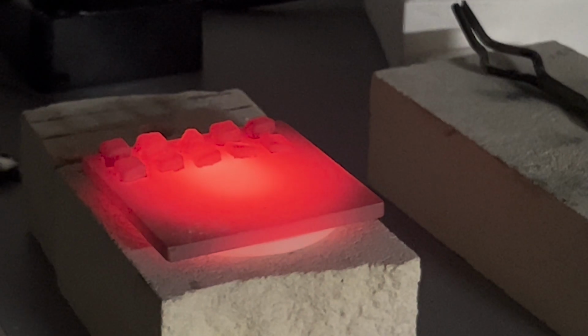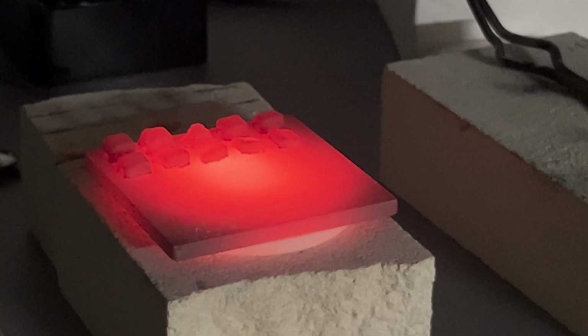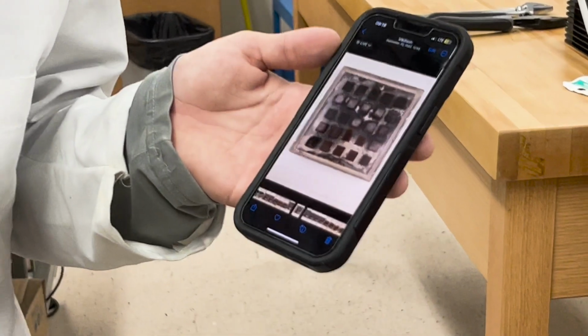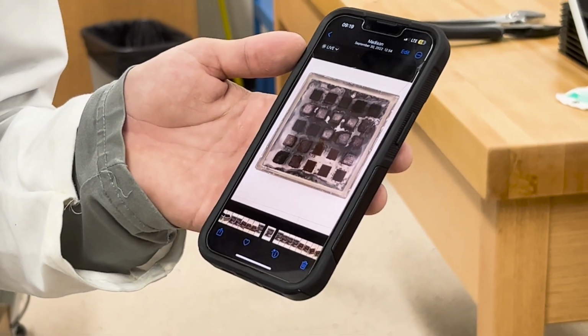Taking that to an extreme example, when you would put an alloy in a high temperature environment like this with oxygen, nitrogen, the things in the air around, the oxygen would get in, react immediately with the base materials and turn them into either volatile oxides or oxides that are going to spall and flake off, which obviously you don't want happening when you're flying at very, very high speeds or in your engine because your material is actively degrading.